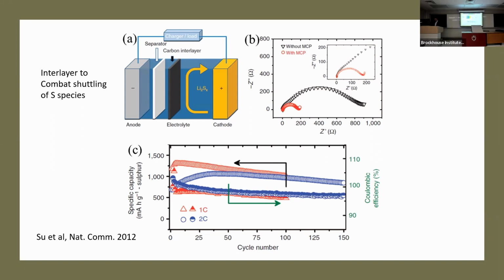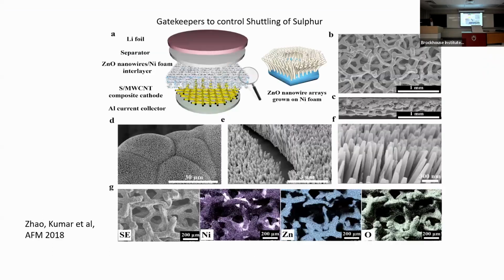And the carbon is not the best material for that, of course. Some materials which have a good reaction with sulfur, such as zinc, and has got a good microstructure like zinc oxide. So you can see that these are nanowires grown on a nickel foam. This is very, very heavy, so you have to make it very thin. And when the polysulfides contact it, yeah, they slow down. They actually act like a traffic signal. They slow down considerably. They therefore allow the electrochemical reaction to take place on the cathode. So therefore, they don't shuttle away.